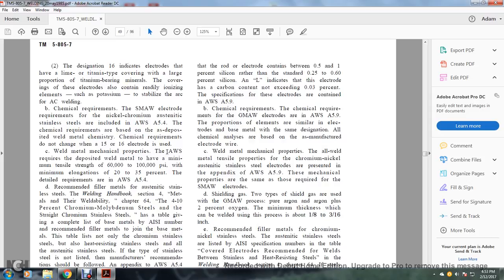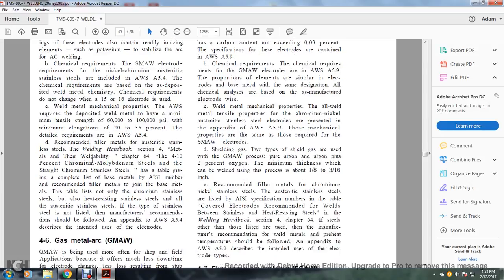Weld metal mechanical properties. The American Welding Society requires the deposited weld metal to have a minimum tensile strength of 60,000 to 100,000 psi, with a minimum elongation of 20 to 35 percent, with the detailed requirements given in American Welding Society A5.4.